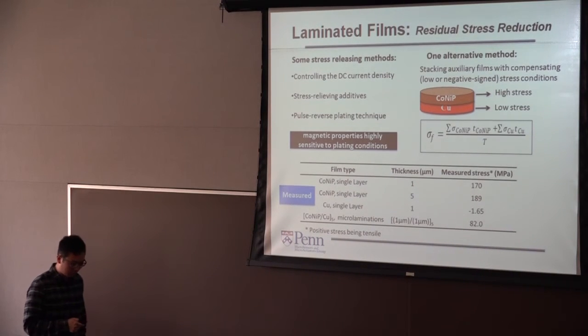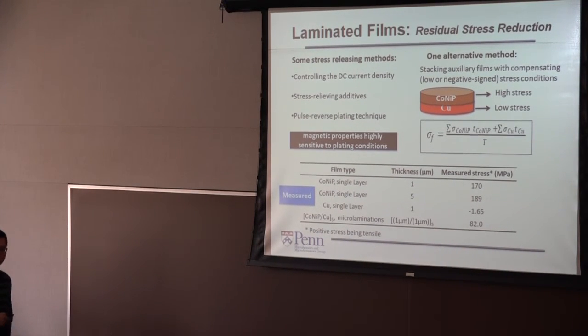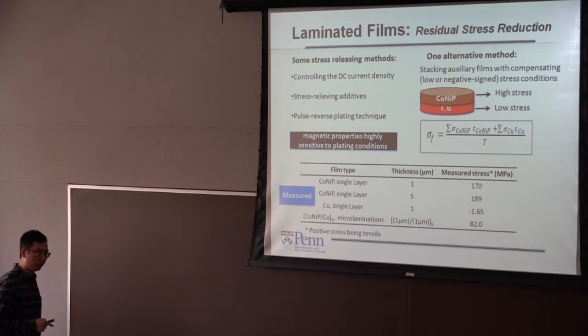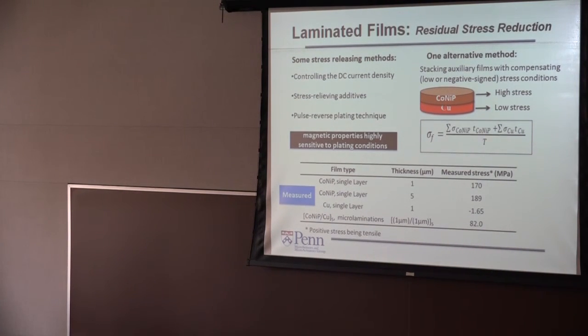We mentioned at the very beginning that mechanical stability is also one of the important factors limiting the overall thickness, so we want to talk a little about that. There are several ways you can reduce the stress so that you can increase the thickness. This includes, but is not limited to, changing the current density, changing the additives, or using some other techniques. But as we know, the magnetic properties are very sensitive to the plating conditions. For cases where the magnetic property is predetermined, say you want a specific coercivity, or an in-plane anisotropy bigger than the out-of-plane, then these techniques might fall short.